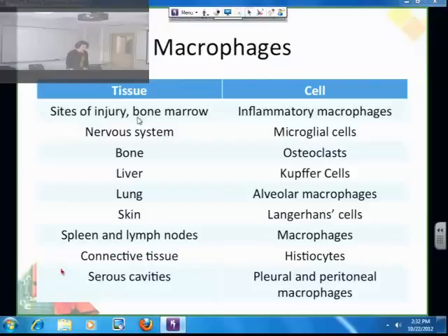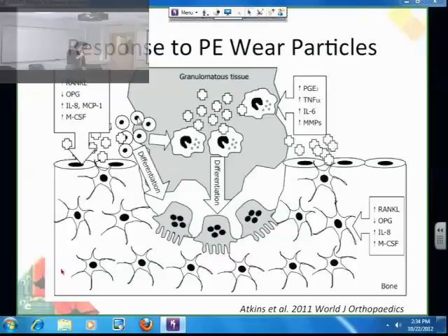It's really interesting. Earlier in this term, we talked about how in an orthopedic implant you might see wear particles being generated after 10 years of articulation of the artificial joint. For example, metal or polyethylene will both have wear particles that form. And what actually happens is those wear particles, which are little foreign bodies, activate macrophages in the bone, osteoclasts.